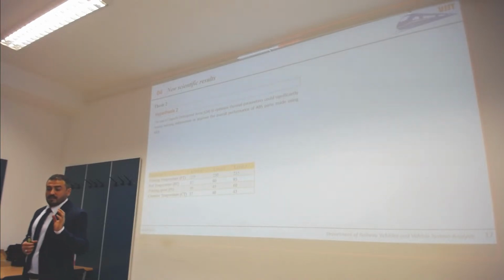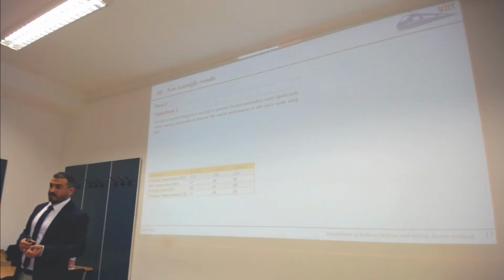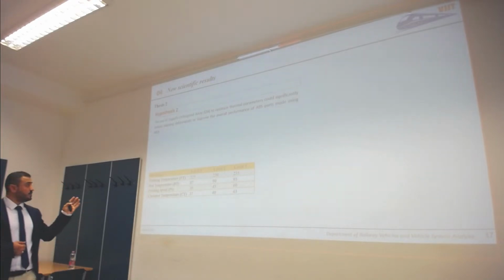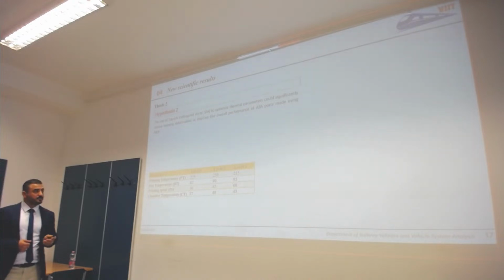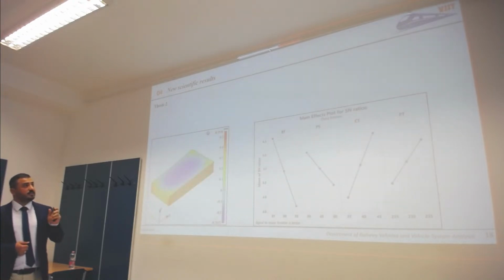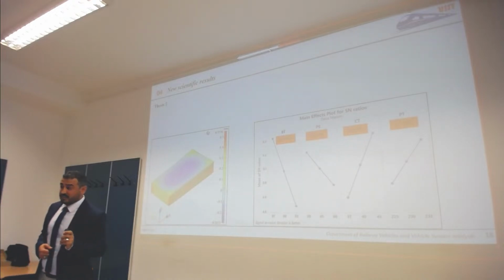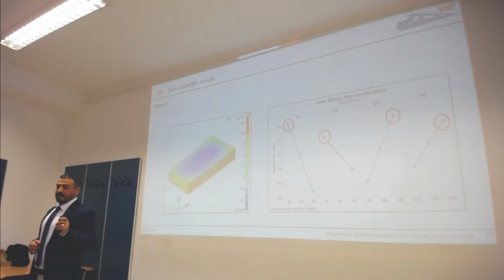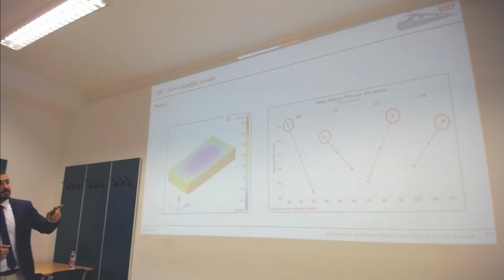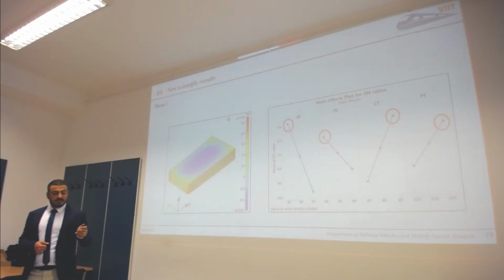Regarding thesis number 2, the proposed hypothesis is that the use of Taguchi orthogonal array to optimize thermal parameters could significantly reduce the warping deformation and improve overall performance. For this investigation, I employed 4 thermal parameters with 3 levels, and I found that the bed temperature was the most significant factor affecting the overall warping deformation. Also, I found the critical and the optimal levels of each parameter to minimize the overall warping deformation.